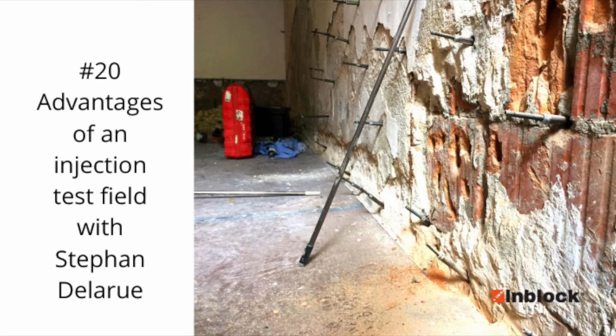So we found out, for example, the distance of the packer from 30 centimeters could be much wider. We choose 40 or 45 or 50 centimeters because we found out during that test injection we get a good spreading, for example. And it was a good result. So the material was traveling between packers quite easily.